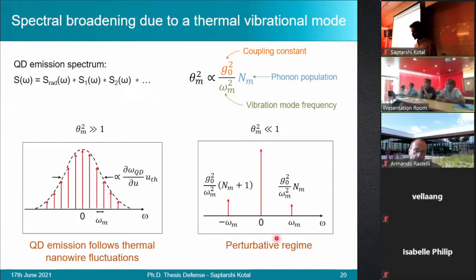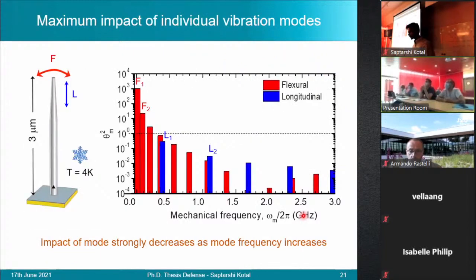We observe a zero phonon line with an amplitude of almost 1, flanked by two spectrally isolated side bands having an amplitude much smaller than 1. This regime is governed by high frequency modes. I programmed a script to calculate the impact of individual modes on the emitter.